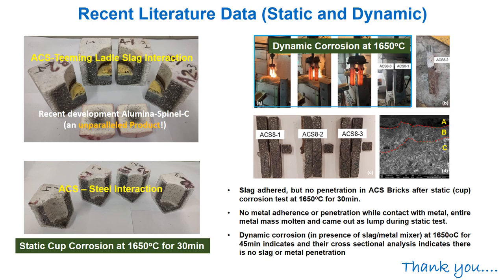The recent development of alumina-spinel-carbon refractories and their static and dynamic corrosion at 1650°C indicates no refractory corrosion in contact with teeming ladle slag and steel — making it an unparalleled product for a teeming ladle. The work has been submitted and will be discussed in detail when published. I appreciate your patience. Thank you.